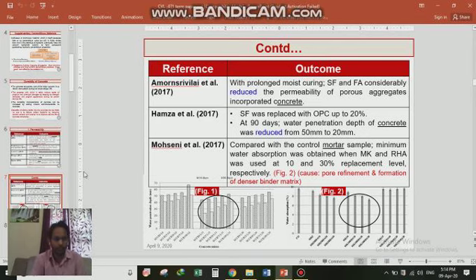In 2017, Amornsrivilai et al. studied the effect of silica fume and fly ash under moist curing condition, and they also used porous aggregate, and concluded that the addition of silica fume and fly ash reduced the permeability coefficient and can increase the durability of concrete structures. In 2017, Hamza et al. replaced OPC with silica fume up to 20%, and it was further concluded that at 90 days, the water penetration depth of concrete was reduced from 50 mm to 20 mm. In 2017, Mohseni et al. compared the control mortar mixes, and it was found that minimum water absorption was obtained with metakaolin, here we can see that metakaolin and RHA